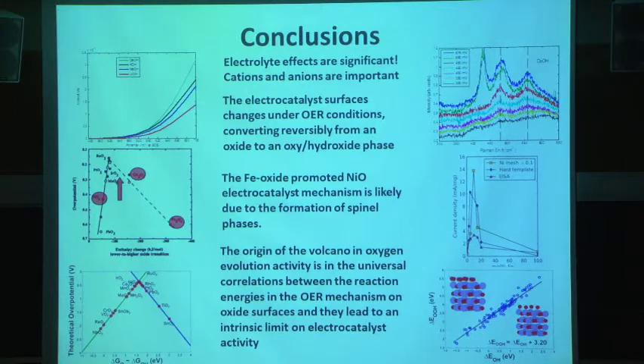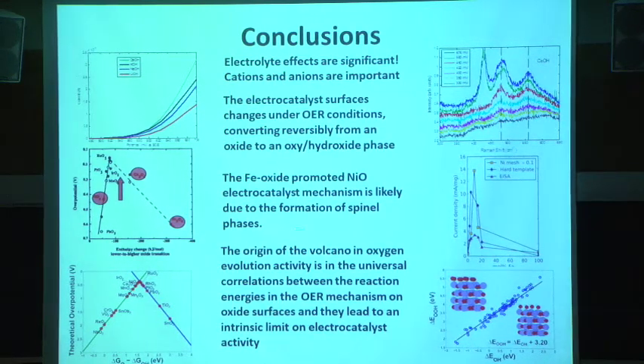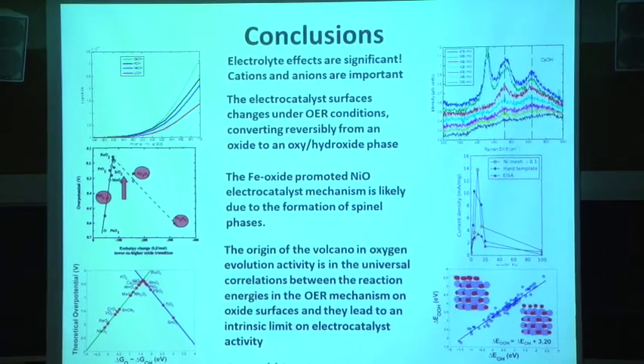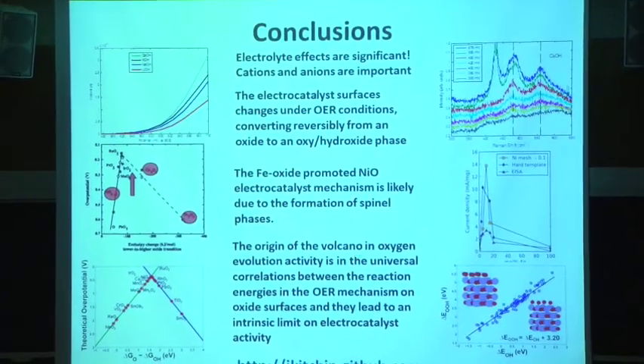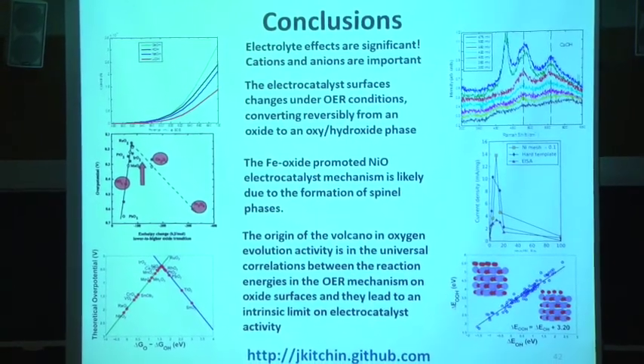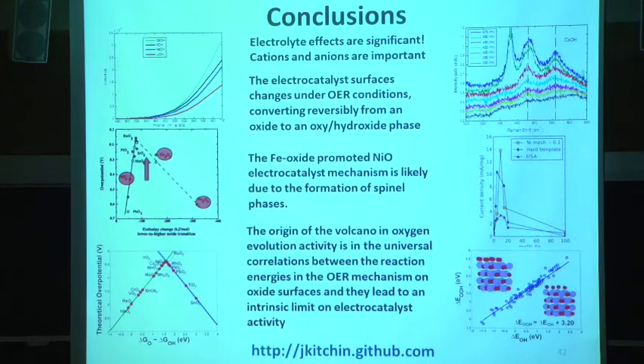The Fe-oxide promoted nickel oxide electrocatalyst we think is due to the formation of spinel phases, but now that I've shown you the oxide surface changes so much under reaction conditions, we actually are going back to figure out whether it's spinel or that the iron is somehow promoting the formation of the gamma phase. Right? And the origin of the volcano is because there are these correlations between intermediates on the surface, and they lead to an intrinsic limit on electrocatalyst activity. So with that, I'd be happy to answer questions, discuss,